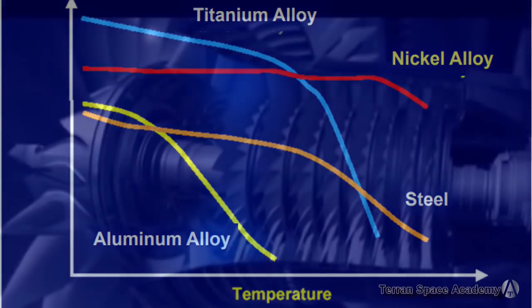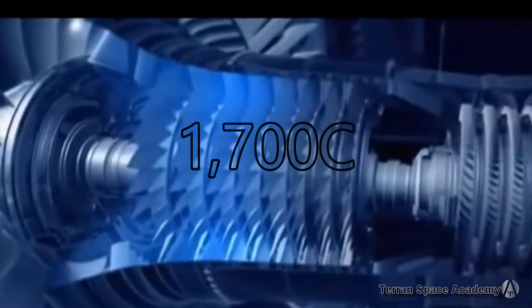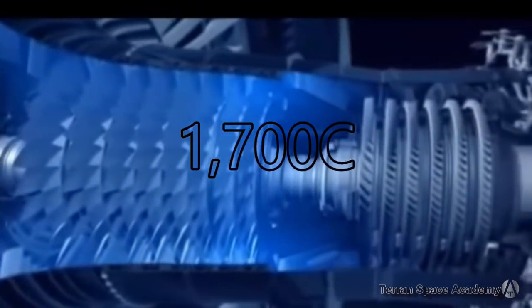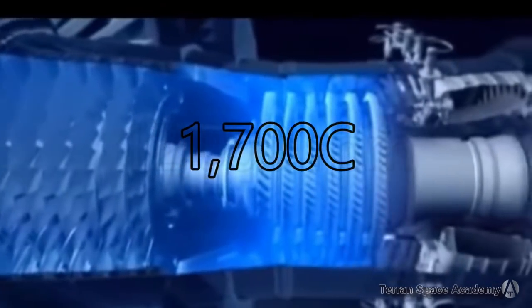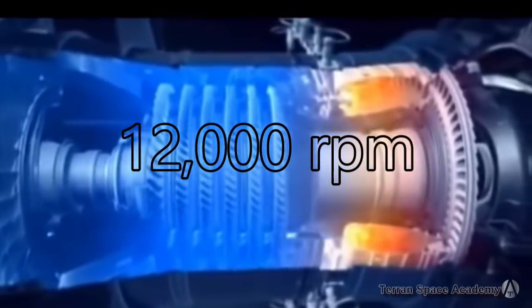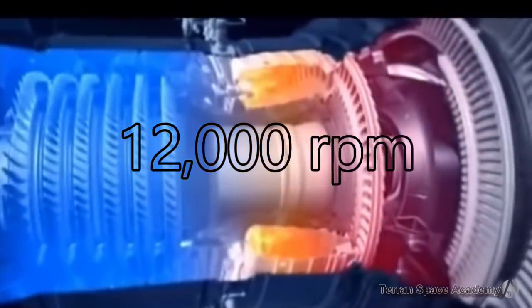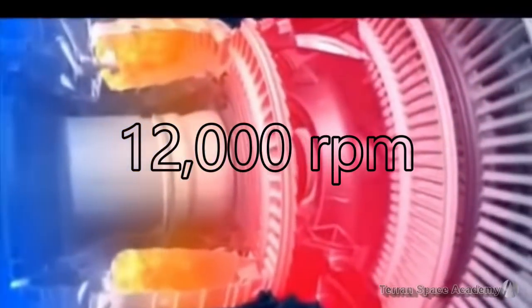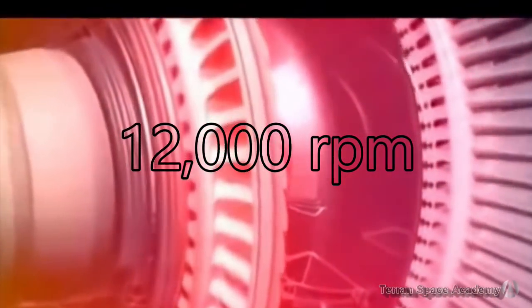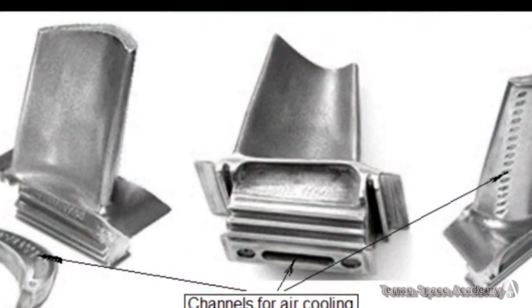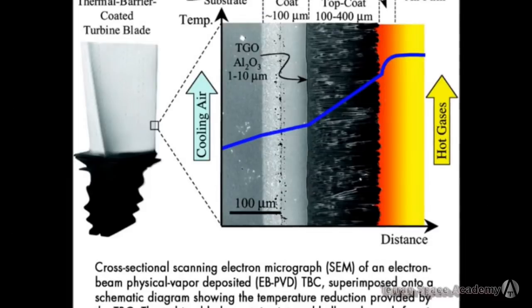The gases from the combustion chamber of a jet engine are at 1,700 centigrade, and the high-pressure shaft spins at up to 12,000 RPM. To keep even Inconel from melting, the blades are cooled by coating them with a low-heat conductive ceramic and have internal channels through which cooler air is routed. Much as fuel is circulated around the nozzle and combustion chamber of a modern rocket engine to prevent overheating.